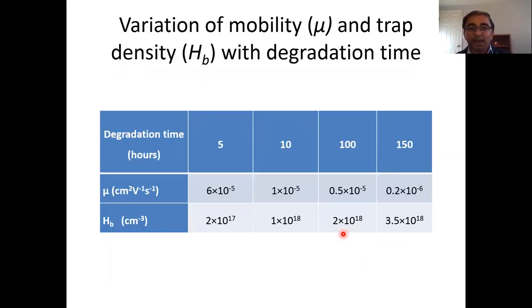So now, why is it degrading? With the degradation time, the trap density is increasing, and we also calculate the trap concentration. How much is the trap density of the traps? How the trap density is increasing with degradation time, and how the mobility of these traps decreases with time. So we have also found with the help of modeling how the mobility of these traps is decreasing and how the trap density is increasing. And this is the reason why you get less and less efficiency with increasing time.